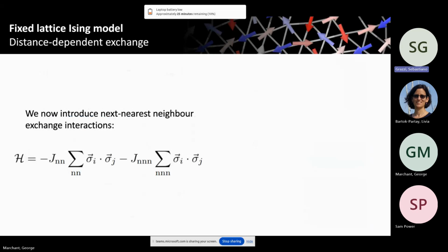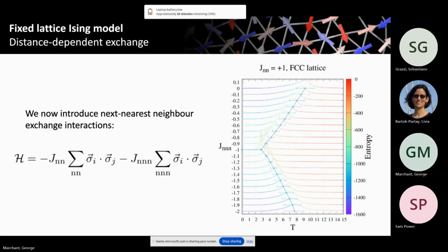And this is actually akin to how real magnetic systems behave. The interaction with nearest neighbors may be described by some exchange constant. As you go further out, the exchange constant can change in size or even change sign. So this is approaching something more realistic, although for regular iron, you can get a decent enough approximation just with nearest neighbor exchange.